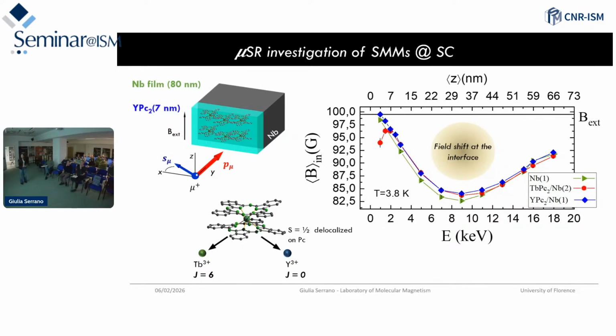We put a 7 nanometer layer on top of niobium of the yttrium Pc2 analog. In this case, we have exactly the same molecule with the same ligand, but instead of the terbium 3+ ion, we have a yttrium 3+ ion with J=0. So we have the diamagnetic analog, and we have just the paramagnetic properties coming from the unpaired electron delocalized on the phthalocyanine structure.